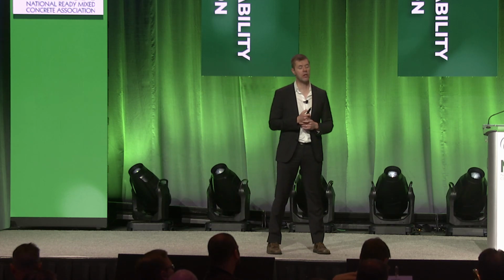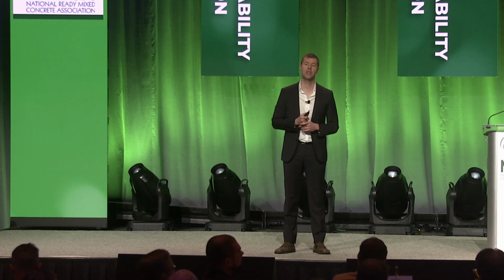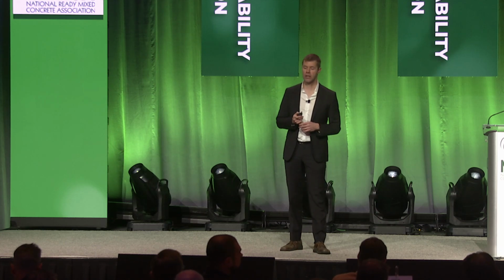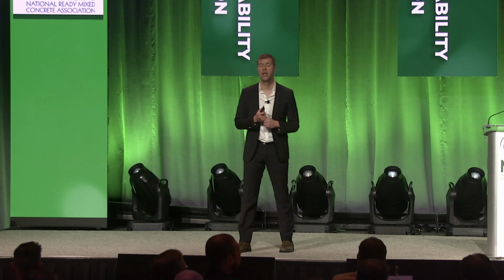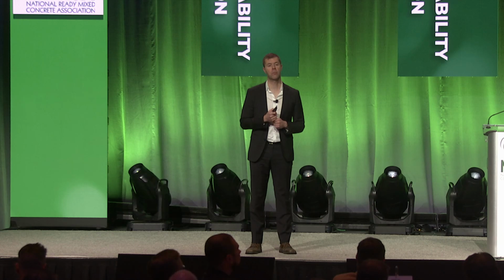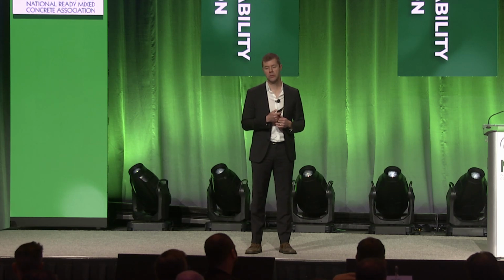Strength could be used as information only, and there are certain states already pushing this. Minnesota's pushing that. Iowa's pushing that as well. And Kenny Seward from Oklahoma DOT has gone on record to say this: if there's a satisfactory maturity measurement on site, then I'm not worried about a strength measurement. That's pretty cool when the DOT is starting to see what they've been doing for years might need to be adjusted, might need to be changed, all right? So we need to start moving in that direction.